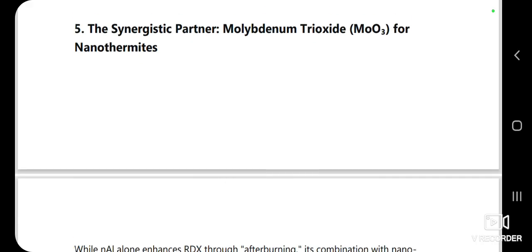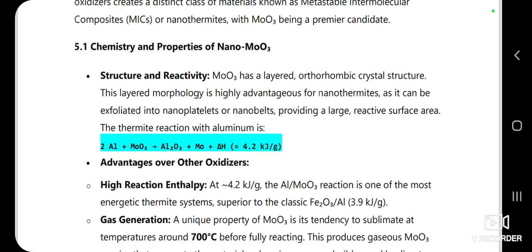Now we study the synergistic partner molybdenum trioxide for nanothermites. While nanoaluminium enhances RDX through afterburning, its combination with a nano oxidizer creates a distinct class of materials known as metastable intermolecular composites, or nanothermites, with molybdenum trioxide. By mixing nanoaluminium with the nano oxidizer molybdenum trioxide, we create a metastable intermolecular composite. Let's look at this reaction. Here we see that two aluminium and molybdenum trioxide react and give us heat of about 4.2 kilojoules per gram.